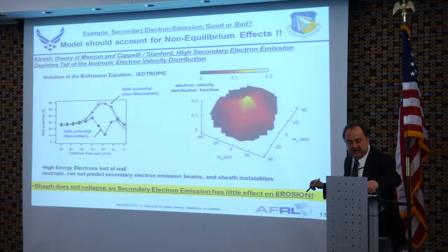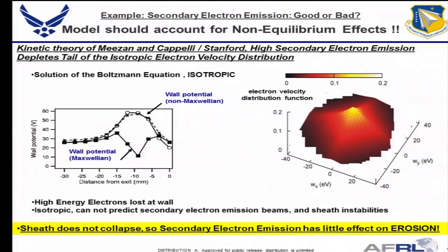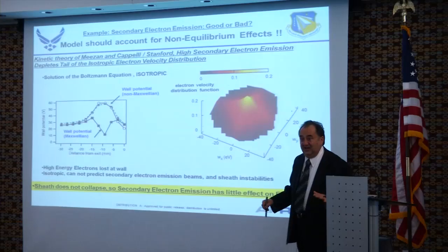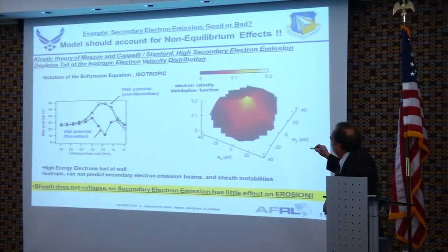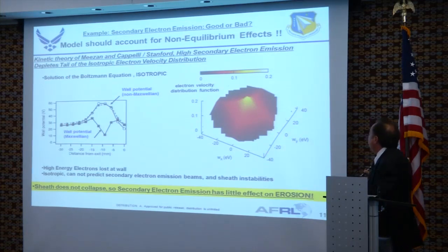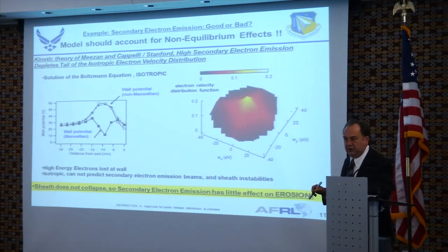After that, in Stanford, they used the Boltzmann equation to find out the non-equilibrium effect, but they cannot do the anisotropic one. They can only do the isotropic one. You know, most of the densities around here, if you see that, well, wall potential does not even change. You see, you can get two completely different answers with two completely different models. So one has to be very careful what kind of tools they are using. In this case, it didn't change. So the conclusion of this sheath does not collapse. So secondary electron emission has little effect on erosion.